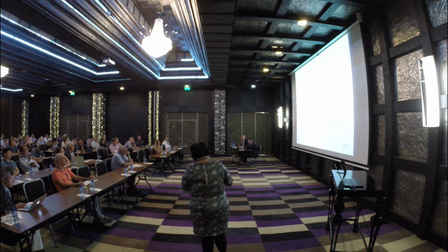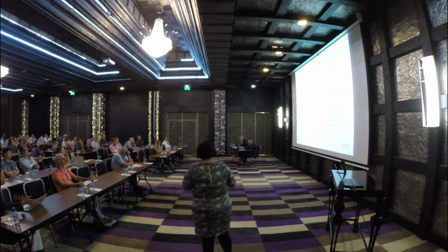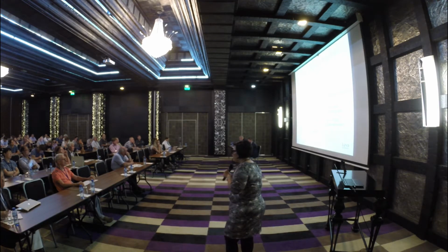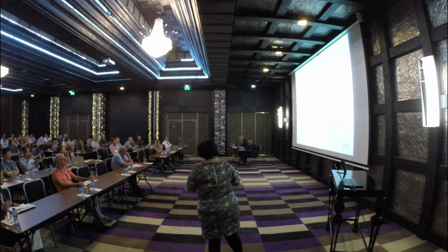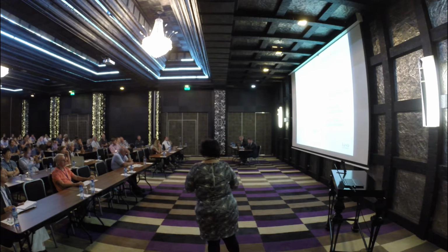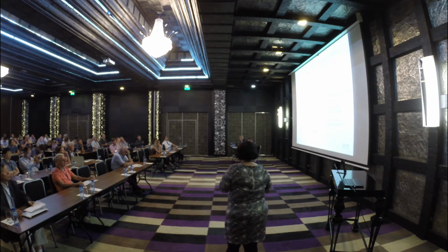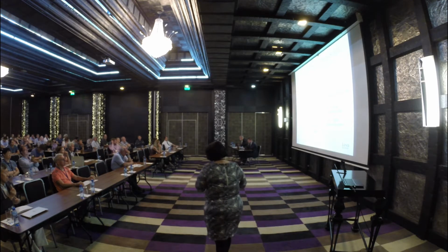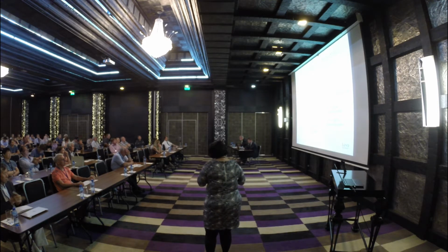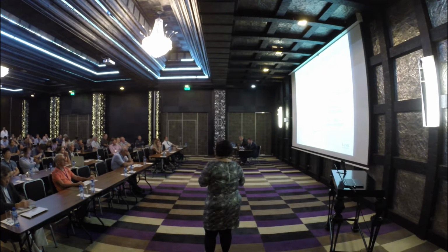What we can also see is that the slopes here are not the same. This indicates that the Young modulus is actually size dependent. So if we try to calculate the Young modulus for those 3 sizes, we'll have different values. And if we look at the top points here, it's when the behavior transits from elastic to plastic.